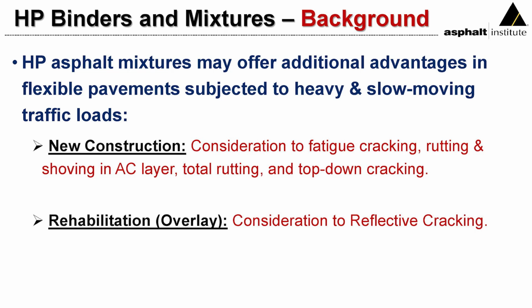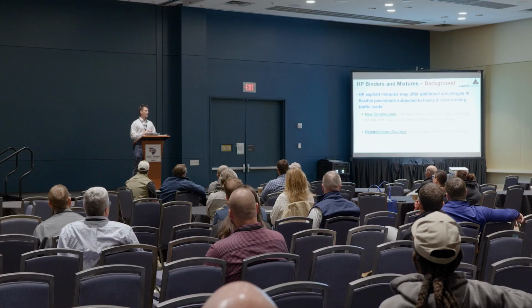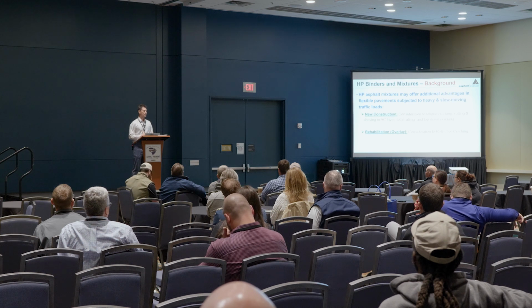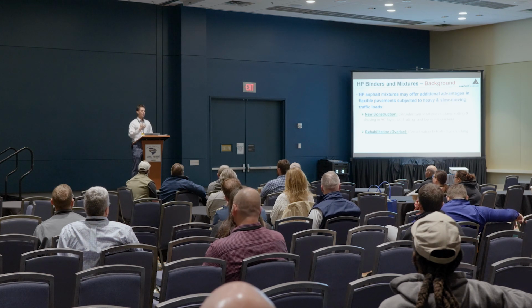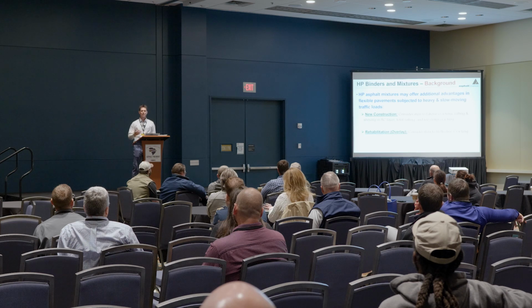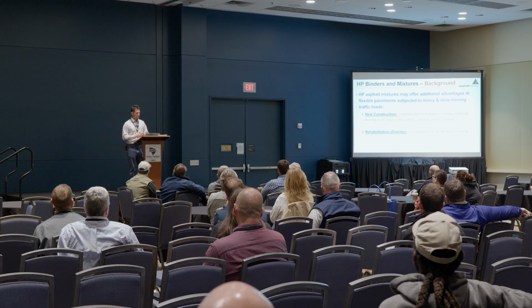So the genesis of high polymer was that you had these really extreme conditions. I would describe it this way: if you're dealing with such an extreme condition that you're considering moving to concrete pavements, okay, this is kind of the last resort. Can you stop the rutting before it gets converted to a concrete pavement? And we've seen situations, at intersections with heavy loads, where you just can't resist the rutting that's happening. Okay, so initially high polymer was for those extreme applications. However, we've really seen that expanded into many different applications in more recent years.